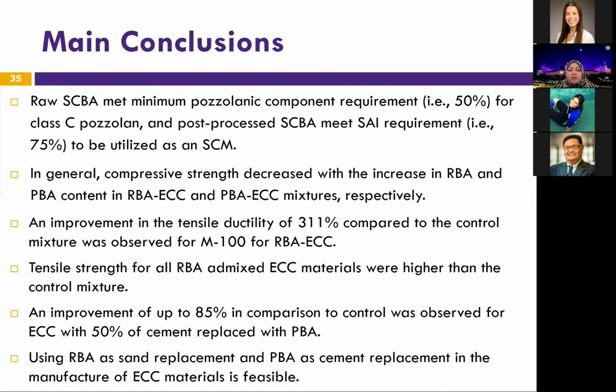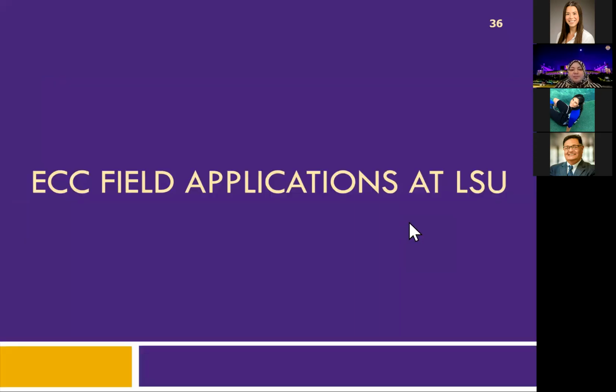An improvement of up to 85% compared to control was observed for ECC with 50% cement replacement with processed bagasse ash. So in conclusion, using raw bagasse ash as sand replacement and using processed bagasse ash as cement replacement is feasible, and that's going to reduce the cost of ECC drastically.